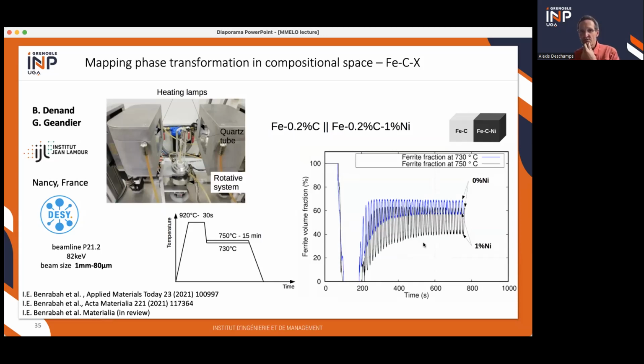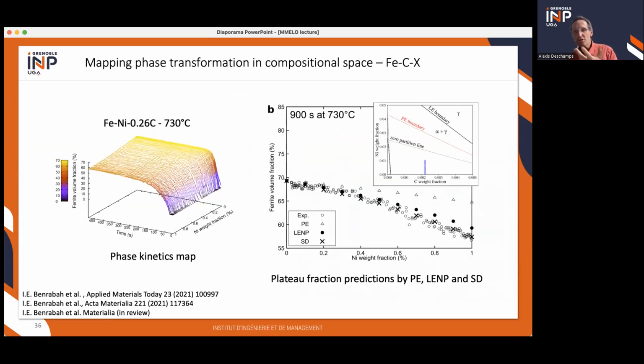And then you can try to extract the relationship between composition, time, and fraction. And you can get this kind of data, which is a set of many different phase transformation kinetics for all the compositions of here nickel between 0 and 1%. So 0 is here, 1% is here, and time is going left so that you can see the graph. So this is a lot of data in one single experiment that lasts about half an hour.